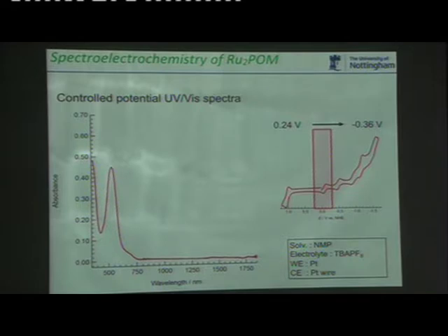This ruthenium polyoxometalate keeps the same electrochemistry that we expect from the polyoxometalate. If you look here, as we go towards the negative direction, you've got 1 electron, 2 electron, 3 electron on the POM, before we have this big peak here, which corresponds to the first of the organic groups being reduced, the 2 terpyridine groups. But then I have another POM reduction before the second terpyridine is reduced. So brilliantly, like what I was talking about before, when I said we have this fingerprint to follow the redox chemistry of these things, we can do it again.